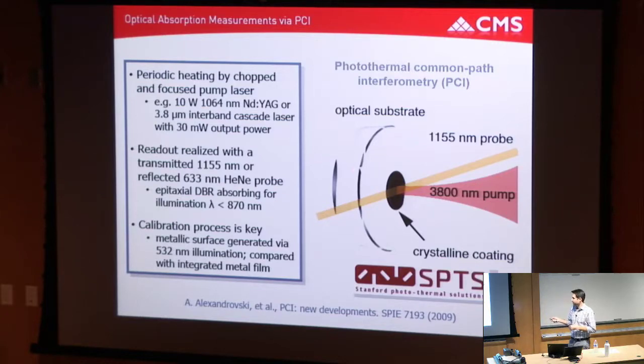If you're on a known substrate, and there's ways to calibrate this that I won't go into, you just need to know the thermomechanical properties of the substrate. So choose something like fused silica, which you know. You have this very thin film absorber where all the heat's dumping into the fused silica substrate, and you're primarily seeing the thermal lens from the substrate. And then you have a probe beam that interferometrically reads out the displacement of that thermal lens. And you can measure to sub-parts per million the absorption in these structures. So we have a custom PCI system built by Stanford Photothermal Solutions, which is a spinoff of LIGO.